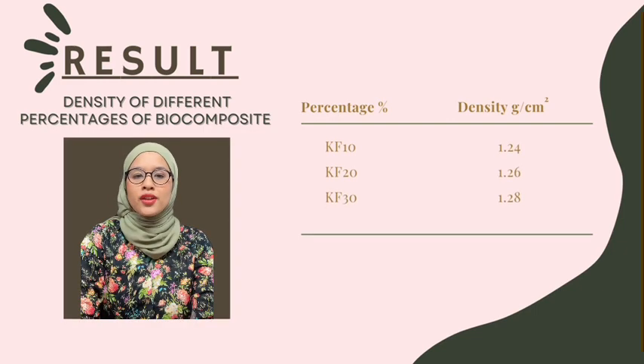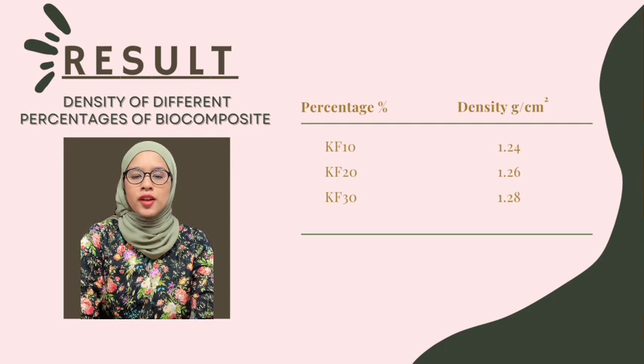Next is the result for physical properties. The density of PBAT reinforced with Kenaf fiber was studied at 3 different percentages, which is 10%, 20% and 30%. The results showed that KF30 had the highest density, which resulted in lower porosity and better mechanical properties compared to KF10 and KF20. Determining the density of a composite helps to determine other properties such as chemical and physical properties, tensile strength, thickness, swelling and water absorption.